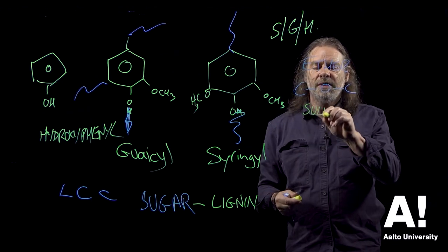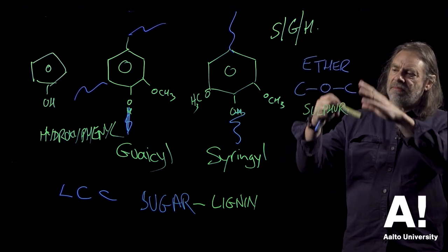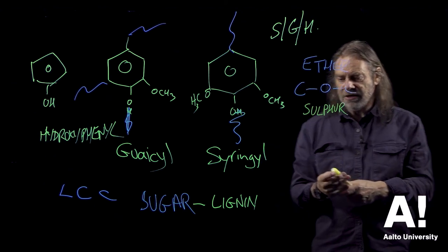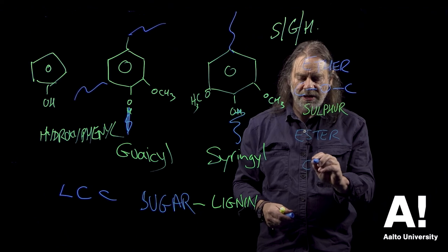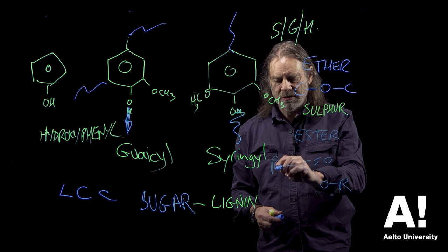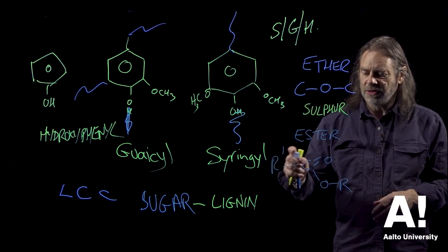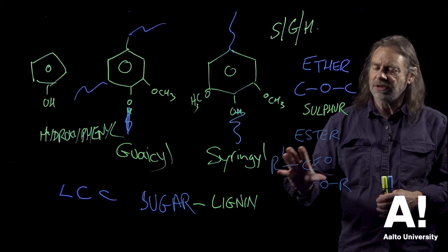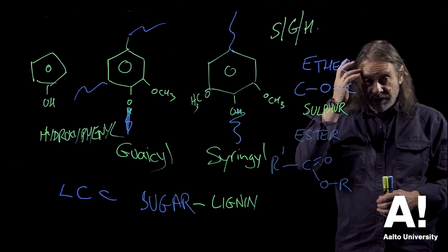To break that bond you have to use sulphur, because in sulphur pulping reactions there aren't many chemical reactions that will actually break ether bonds — they're fairly limited. In grasses, we don't have ether bonds, we have ester bonds. Ester bonds are much more easily broken; you can use alkali to hydrolyse them. So lignins in grasses are much more easy to remove than lignins in wood — we don't need sulphur pulping for lignins in grasses.